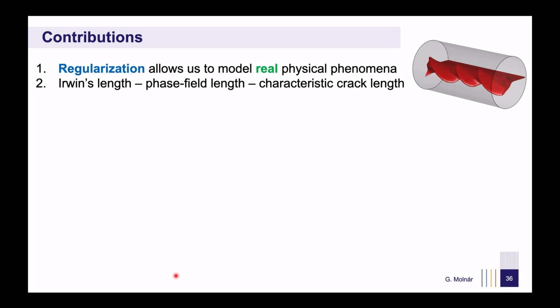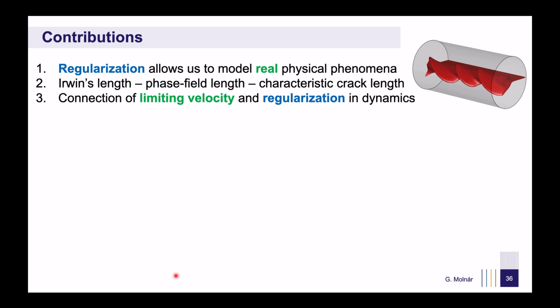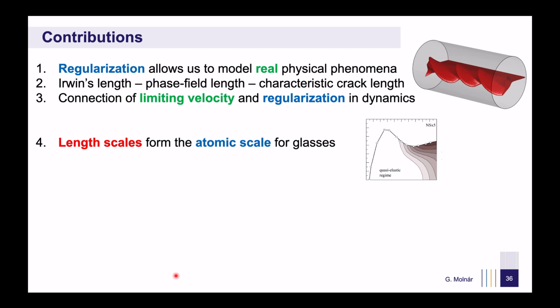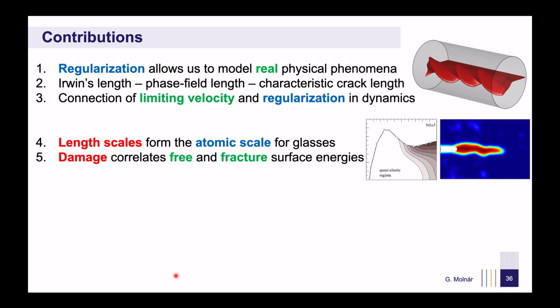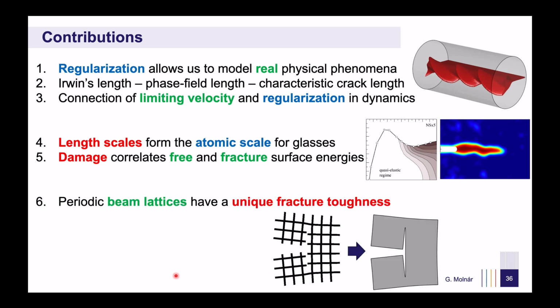This regularization mechanism is what allows us to recover experimentally observed dynamic crack velocities. Furthermore, we have demonstrated how length scale can be measured in real materials using silica as a case study. Additionally, we showed that damage diffusion allows us to correlate free surface energies with fracture surface energies, addressing a long-standing question in fracture mechanics. Finally, we used regularization to demonstrate that a unique fracture model exists for lattice structures.